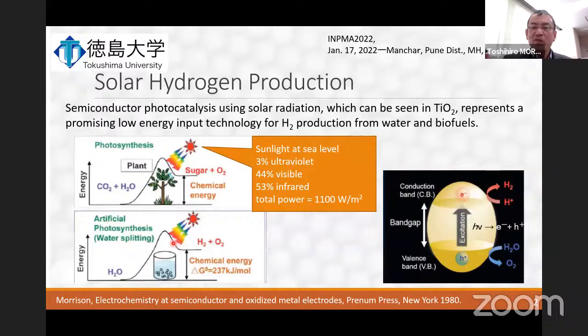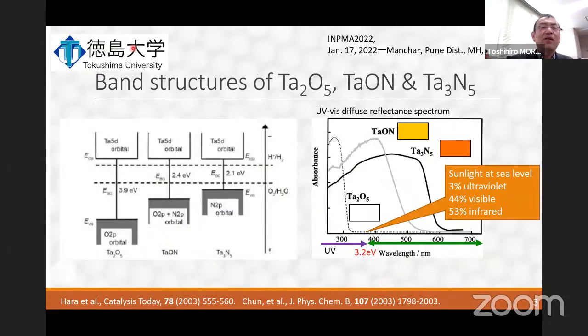Light energy is consumed for excitation of electrons from the valence band to the conduction band in semiconductors. But TiO2 uses exclusively ultraviolet rays. That means titanium dioxide can utilize only 3% of sunlight. To improve the efficiency for hydrogen production, it's necessary to choose a smaller band gap material to achieve the visible light driven photocatalytic reaction.